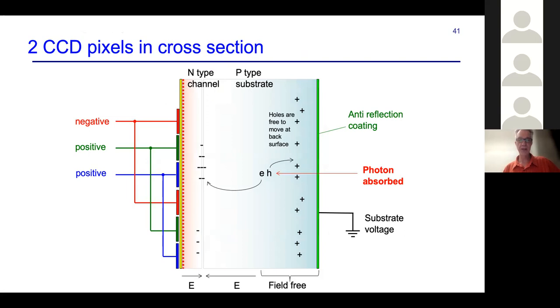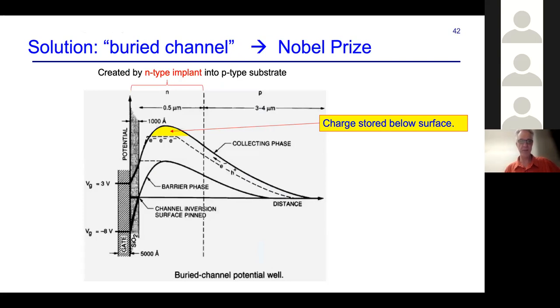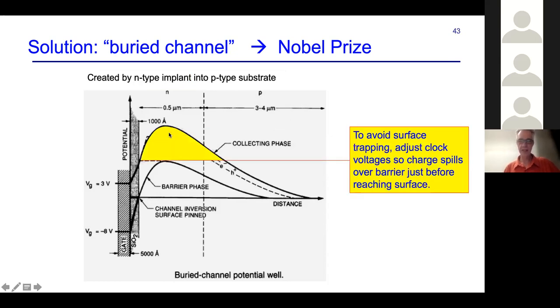that what they could do is drive the electrons into the bulk material below the surface where there are very few traps. And so here we can see in the new potential diagram that the charge rolls downhill, down as the top of the page in this case because electrons are negative. You can see that they roll to the bottom of the potential well, which is marked in yellow. And then as the charge fills up, they nearly reach the surface, but before the charge actually comes into contact with the surface, it starts to spill over the barrier potential, which is drawn as this other line here.